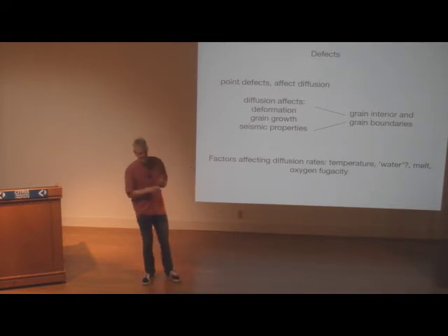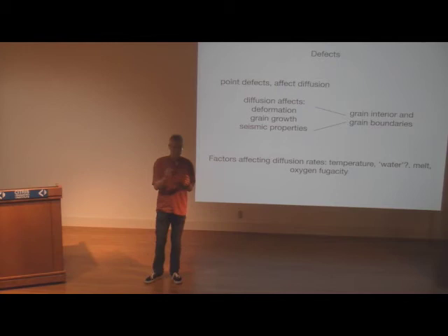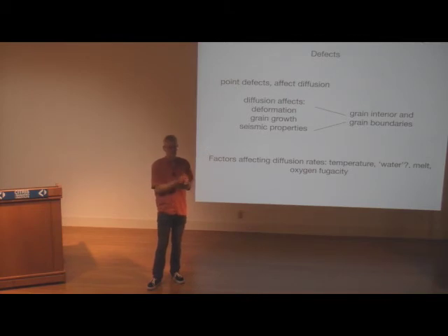Yeah, the idea is that in anhydrous olivine, the titanium as a 4+ ion sits on the silicon side. Right? And then as you hydrate the olivine, the titanium moves from the silicon side onto perhaps a pre-existing magnesium vacancy. Right? And then to charge balance it, you have those two hydrogens. So the titanium's in the olivine. If you take natural olivines, they have a range of titanium contents from a few tens of ppm to a few hundreds of ppm. And on hydration, you just move the titanium around in the crystal structure to accommodate the hydrogen.